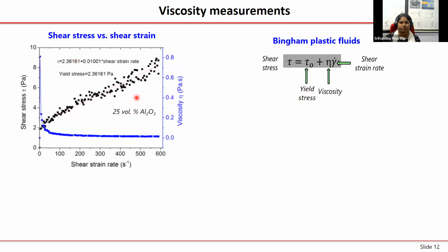We have used a rotary type of viscometer, and we have obtained shear stress and shear strain rates. That particular data is this black data, these data points. In principle, we know that it has a yield stress because it is not a linear graph passing through the origin. That means my slurry is essentially following a Bingham plastic behavior. It is not a Newtonian fluid. Water is a Newtonian fluid, but here the slurry is not. So you can use this expression to find out the viscosity. Essentially, look at this particular blue one; it's the viscosity that is plotted.